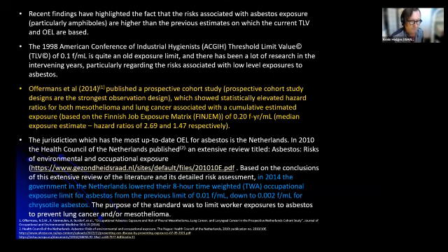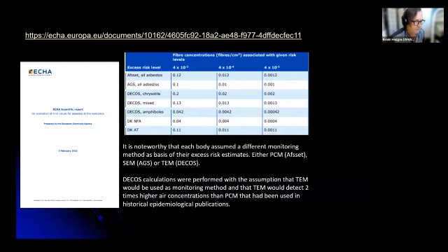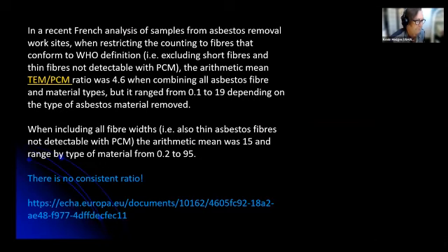And the purpose of the standard was to limit workers' exposure to asbestos to prevent lung cancer and/or mesothelioma. The European Chemicals Agency has this scientific report, and if you look at the column on the left, DECOS, the Netherlands, they've set the exposure limit for chrysotile at 0.002, but that is actually based on transmission electron microscopy. But they do say there's an assumption that TEM will detect 2 times more fibers than PCM.